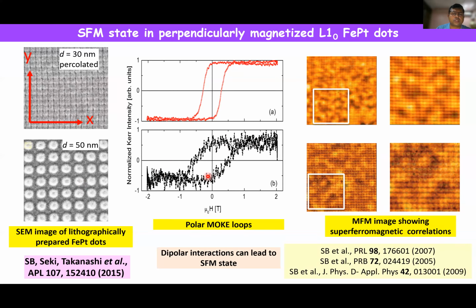One can, of course, argue that this hysteresis is coming from the individual dots, but that's not the case, because you see the magnetic force microscopy image where multiple magnetic dots are coherently switching. So this leads to some kind of correlations among them, which we call a superferromagnetic domain. Some people call it dipolar ferromagnetism, but it's basically the same. We are studying this, and you can find some of the publications here.